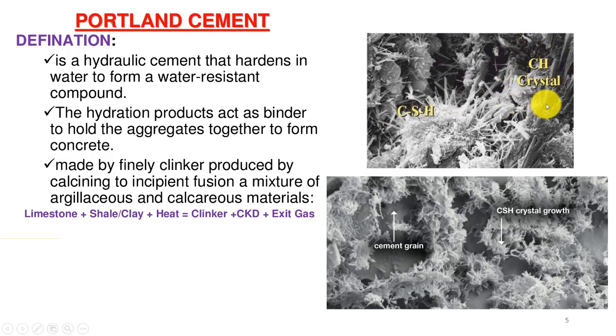While on the other hand, the calcium hydroxide has an ability to dissolve in the water in case of intrudement of water into the concrete microstructure, so that with the passage of time your concrete would be a little porous, and it would be susceptible to freezing and thawing, and degradation with time and environment.